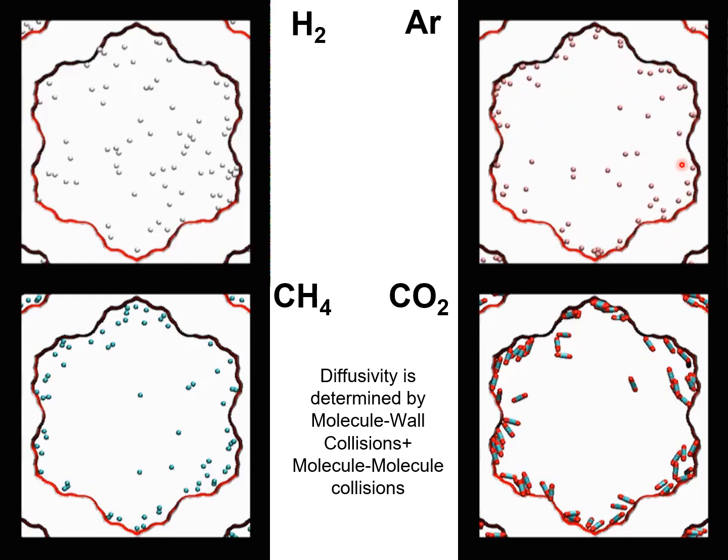And in the core region, it experiences molecule collisions. For methane, that has a higher adsorption strength than argon, there is a higher concentration of methane near the pore walls and a lower concentration of molecules in the core region as compared to argon.